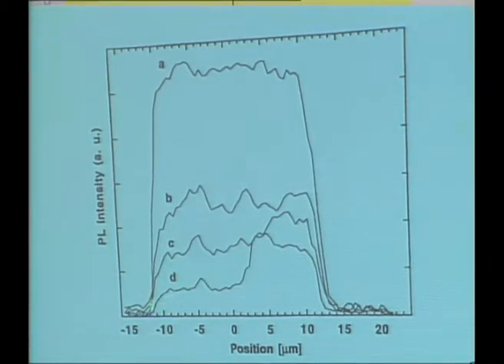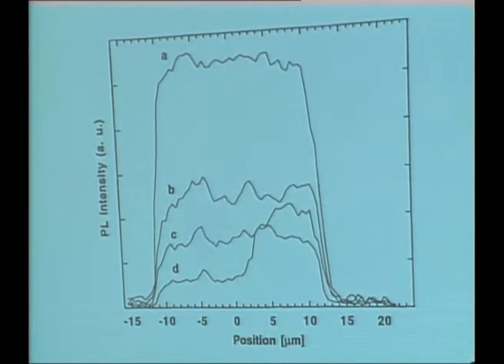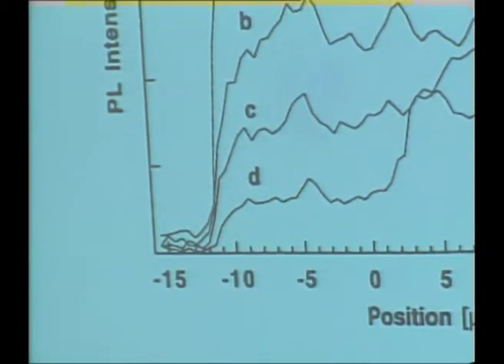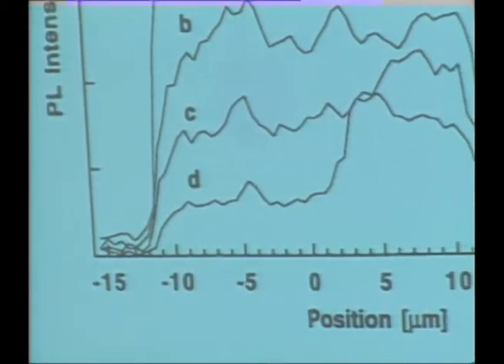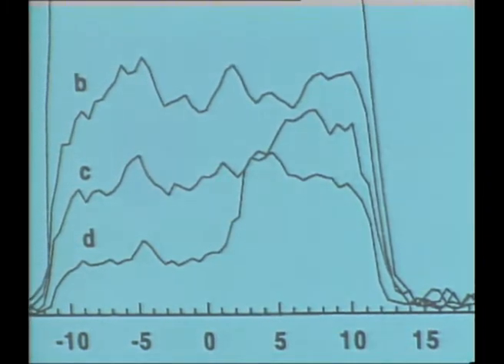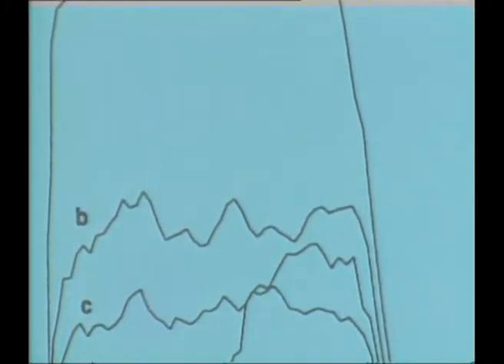As you start to dope the material, and this is the highest level of doping, I don't remember which is positive, which is negative. You're doping one side P-type, the other side N-type. And there is here a little peak in the photoluminescence, which there had to be because you saw it on the photograph. But obviously, it would have been better if this were all the way up to here. So the PIN junction, the I region, is partially quenched.